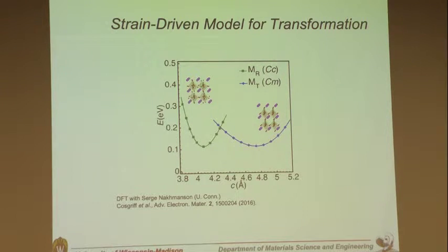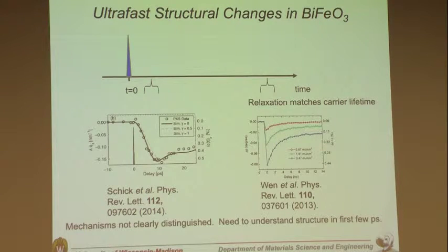And we see the important difference here is that the T is softer than the R, right? So if I expand it a little bit, this expansion that I'm going to expect from the ferroelectrics, the relative free energy is going to favor, let's take each one, we'll grow them so they're in equilibrium. This guy and this guy, we'll choose them so they're the same free energy. We move them each 0.1 angstroms higher, and the energy for the R phase goes up more. So we expect that if we expand this material, then it will favor the T, and the T will expand, the R will contract. Okay, or the R will disappear. Both of them expand in the lattice parameter, the amount of the sample in the R phase will decrease and the T phase will increase.